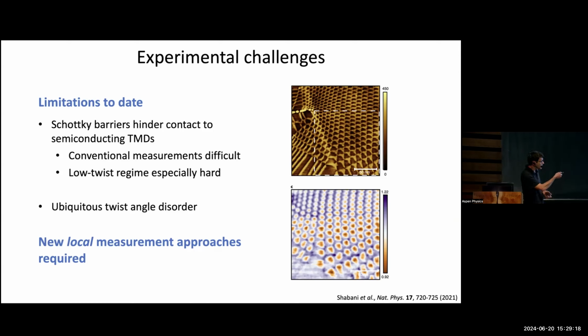The other thing, the dirty secret, or maybe not so secret, of the Moiré community, is that as we are making these samples, we pick up one flake at a time with some polymer stamp. This is sort of jiggly. You put it down, you press. You try to be gentle, but you have some uncontrolled strains and forces that you're applying as you assemble these samples.